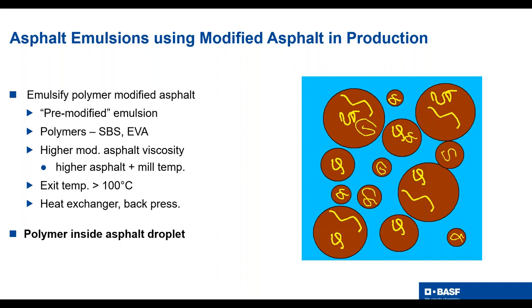Typically a lot of plants making microsurfacing emulsion will have heat exchangers for both of these processes, because you usually want to have the emulsion out to the contractor at around 120 Fahrenheit, which is about 50 degrees C in those applications. The cooler emulsion helps in their mix, break, and cure time. So again, heat exchangers are used anyway in both the applications.